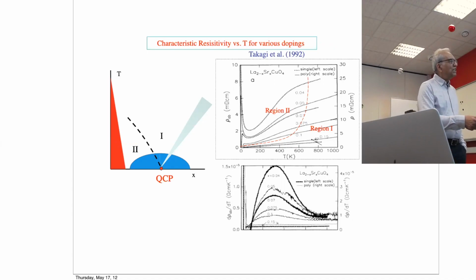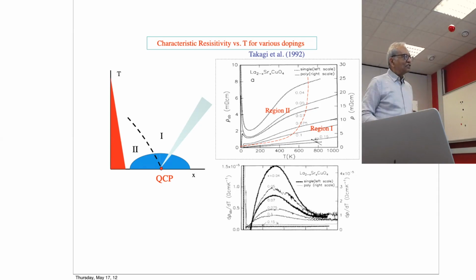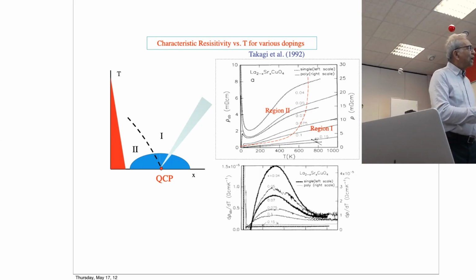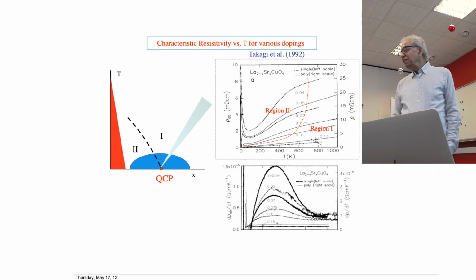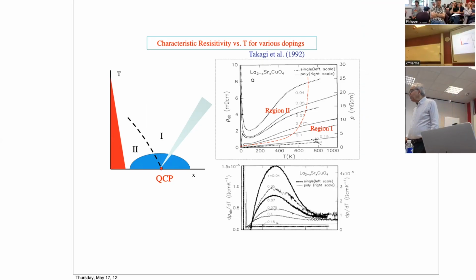How linear is it? Let's take the derivative d rho over dT, and that's what this is doing. And then as you cross over into this region, the resistivity begins to change, and I've roughly marked this boundary. So in here also the resistivity is linear for some temperature, and then it does funny things. And here's the derivative. You can see more carefully this boundary of this change. I have purposely not continued this dashed line further because we don't really know. Samples become dirty and different materials begin to behave somewhat differently there.